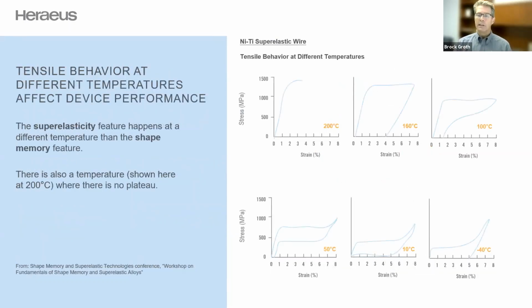And so diving in, kind of combining what we've looked at in the stress strain curves and what we've talked about in the temperature relationship between the transition temperature and the environment that the device is performing in. Now we're combining those, and what we have here is a series of 6 graphs of the same hypothetical material being tensile tested at different temperatures. So this is all the same material. The only thing that's changing is the temperature that the tensile test is being completed in. So if we look in the lower left-hand corner at 50 degrees C, this is the standard superelastic loop that